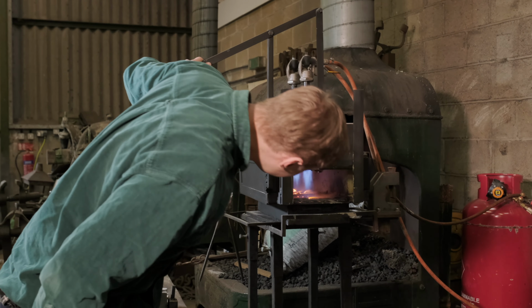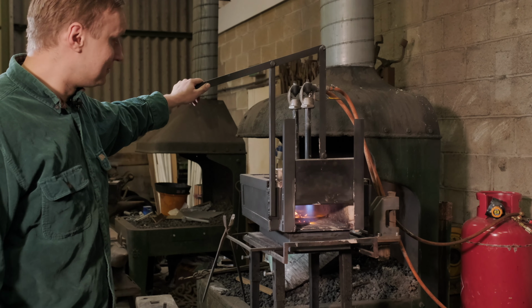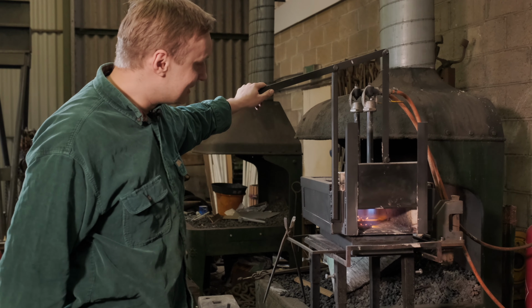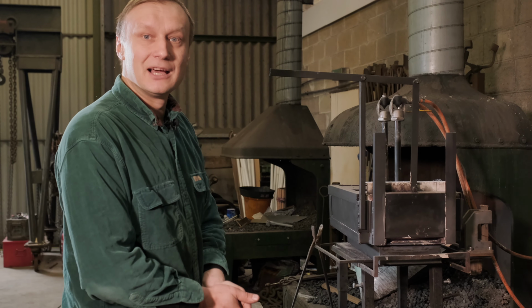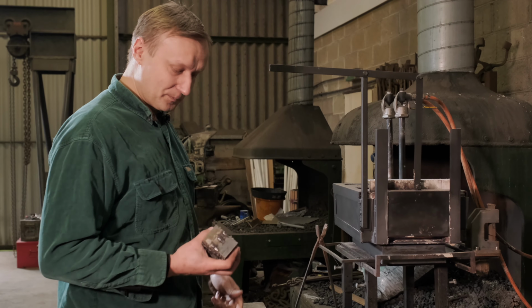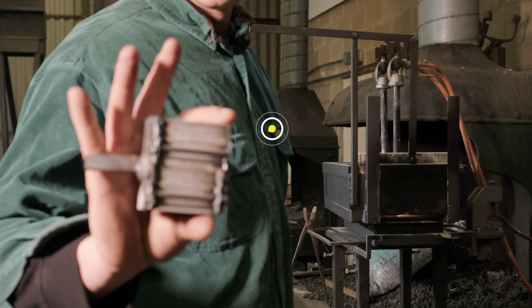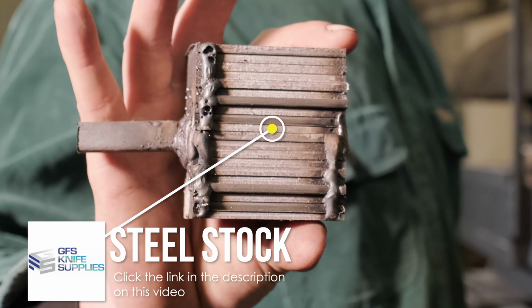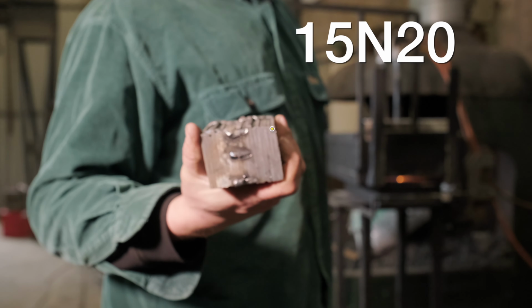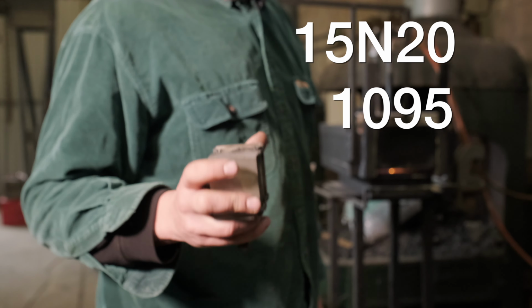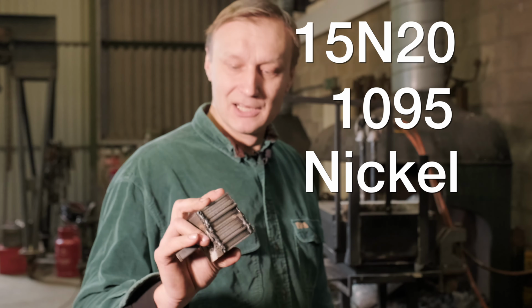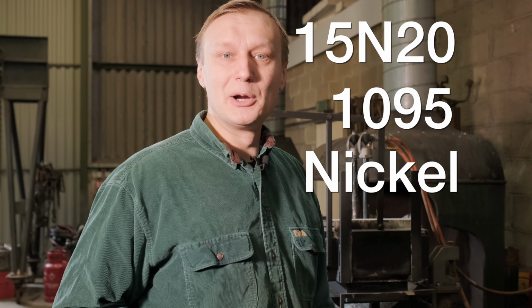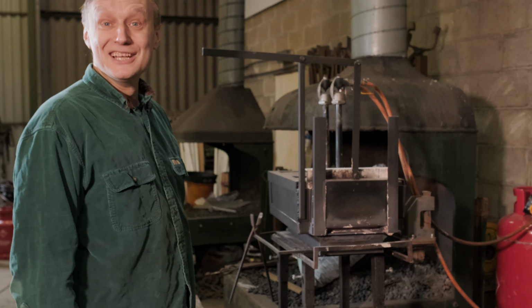First things first. Let's get the temperature up. So this will need about 10 minutes to get to temperature, and then we're gonna put the stack in. So what we're gonna start today is 30 layers of steel, classic mix of 15N20 and 1095, and a bit of pure nickel inside to get a bit of a brighter pattern. And we're gonna try something new. I haven't done that pattern before, so I have no clue how that's gonna turn out. So looking forward to that. And now we wait, essentially.